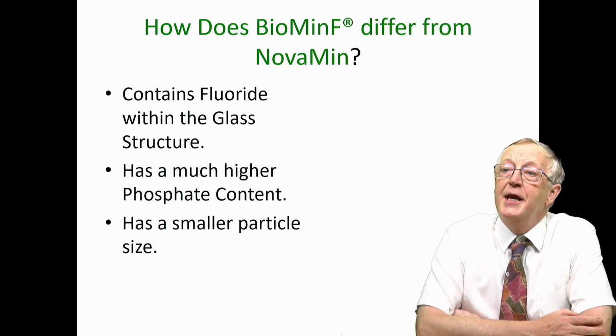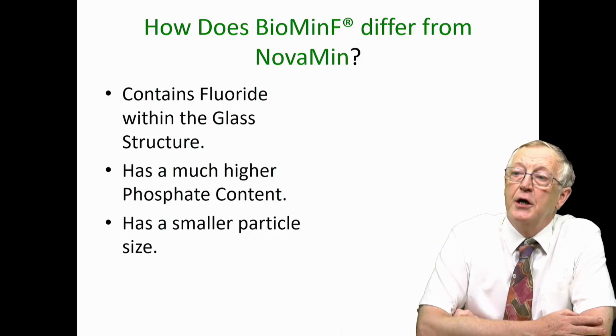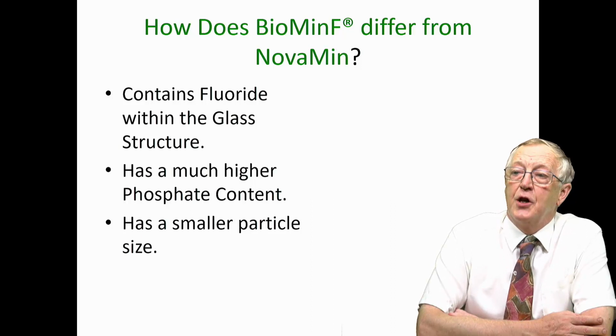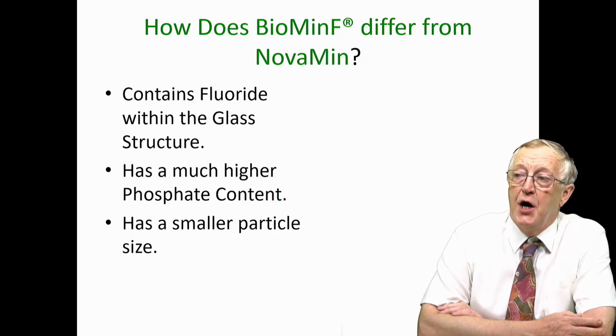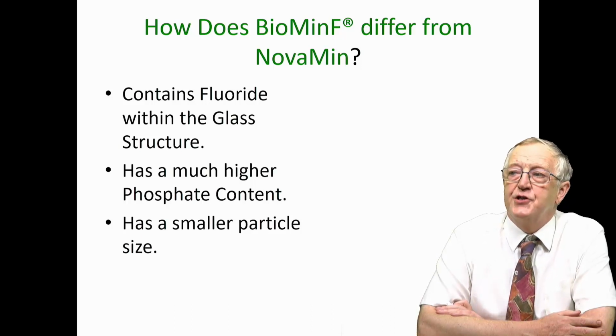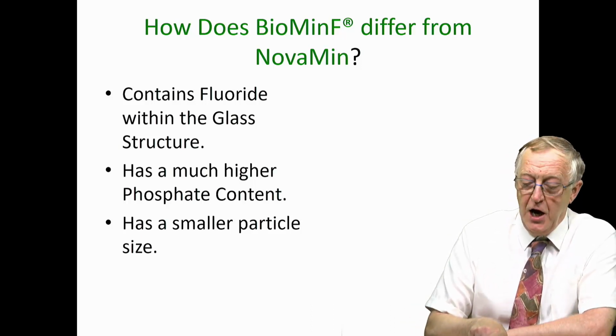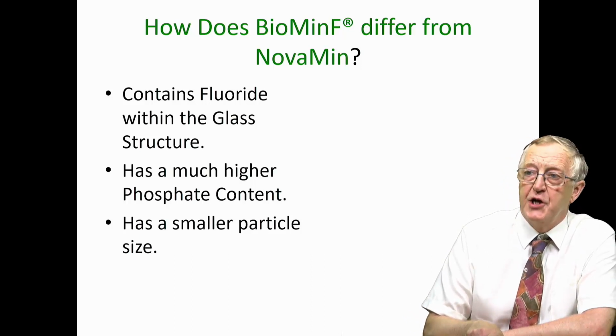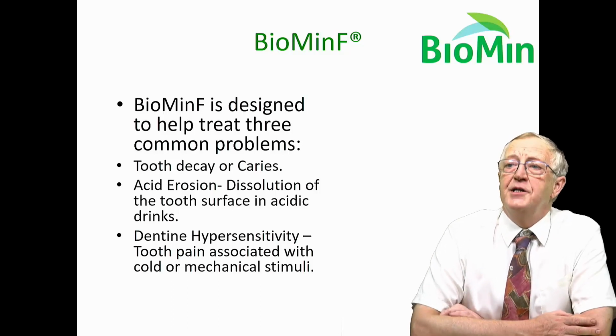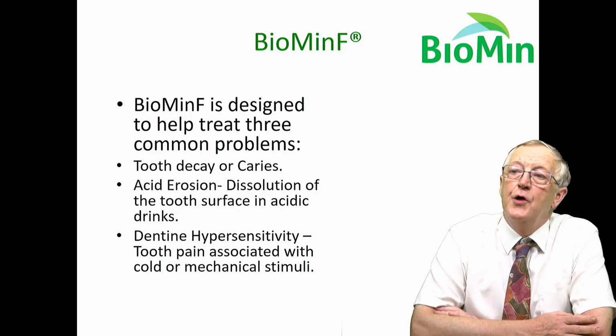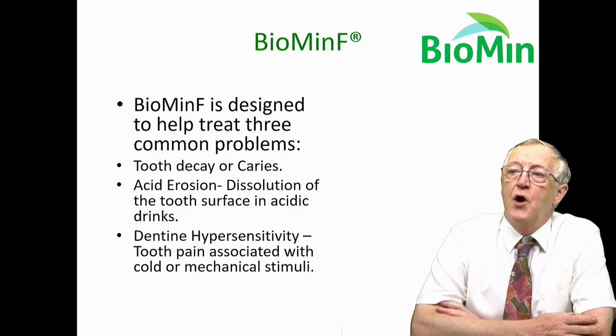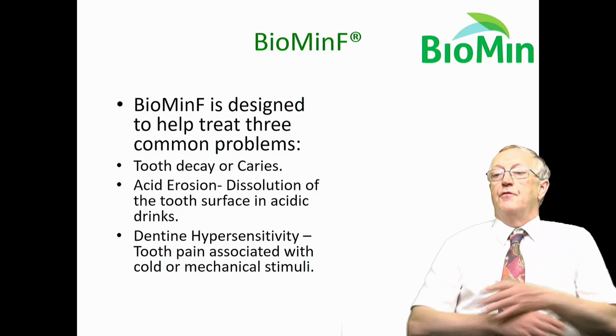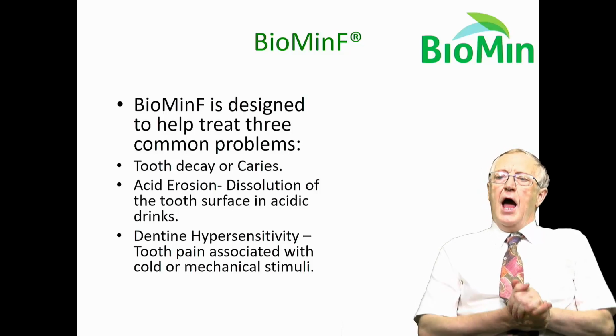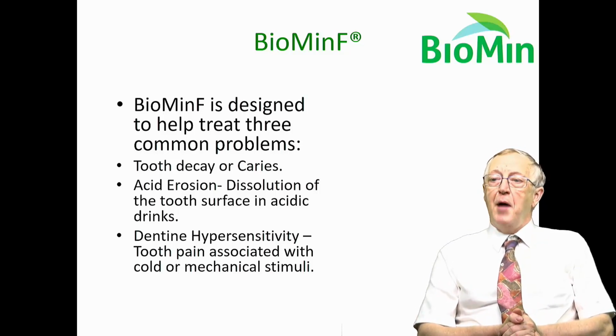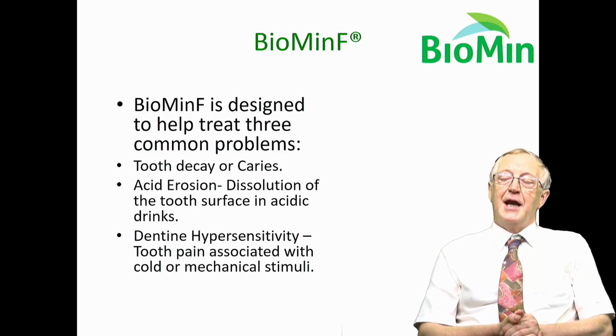It differs from the Novamin in that it contains fluoride within the glass structure. It has a much higher phosphate content in the glass, and it has a smaller particle size. All those changes are designed to improve its efficiency as a toothpaste for treating dentine hypersensitivity and for promoting remineralization. The Biomin F toothpaste is designed to treat 3 common problems: tooth decay or caries; acid erosion, which is the dissolution of the tooth surface, for example in acidic drinks in the absence of bacteria; and dentine hypersensitivity, which is tooth pain associated with cold or mechanical stimulation.